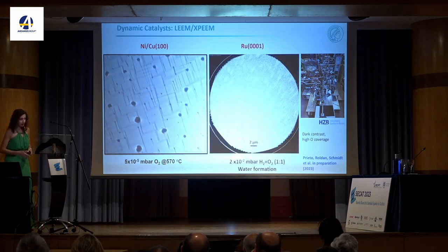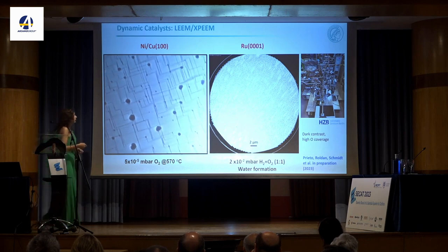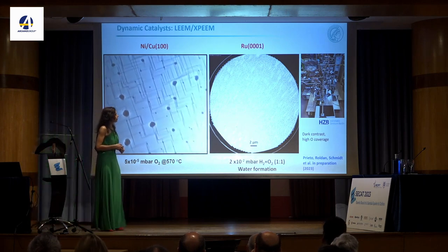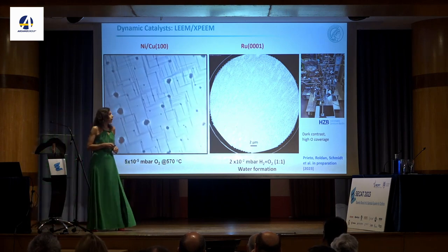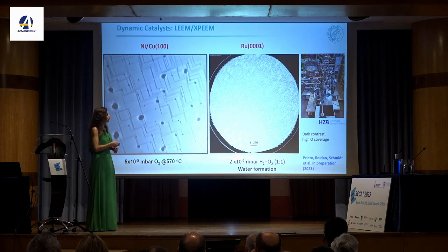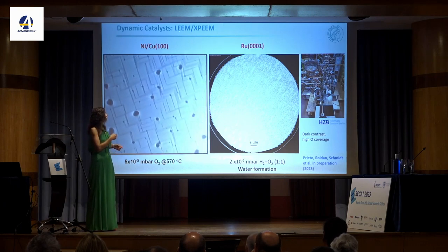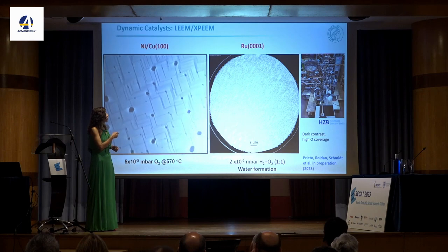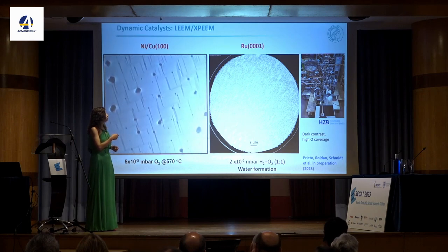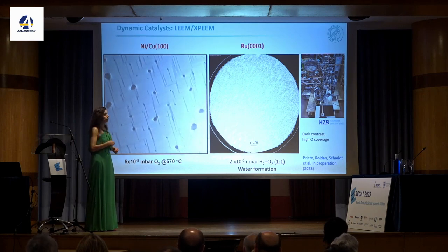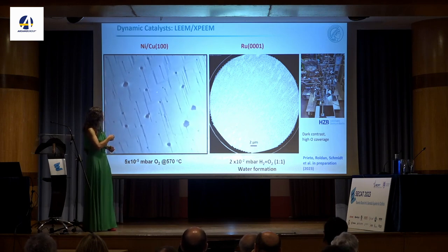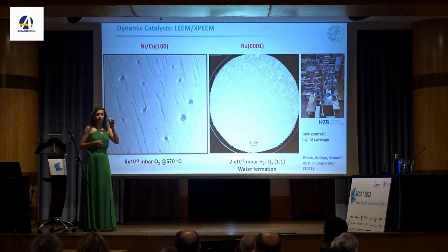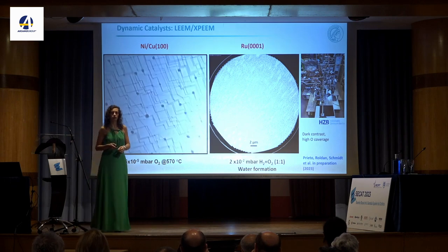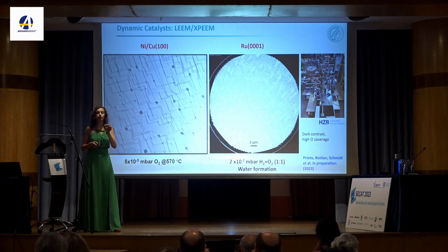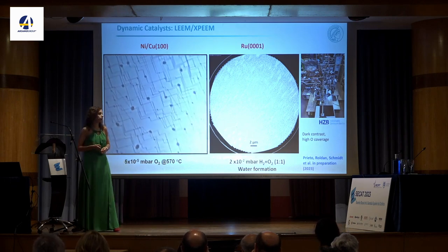Now, another example here, by the way, these data here are acquired with a low-energy electron microscope, and we have a beamline from the Max Planck Society in Berlin, where we have this low-energy electron microscope, also at the beamline, so we can get microscopy and spectroscopy spatially resolved. So I can go to different areas of the sample and take NEXAFS spectrum or XPS spectrum and tell you what is the local structure and what is the local composition of the material and oxidation state.